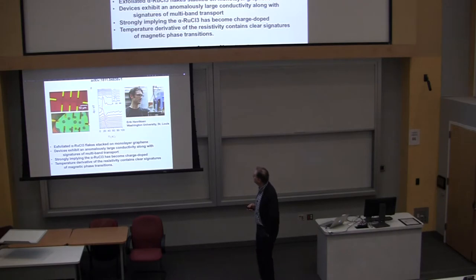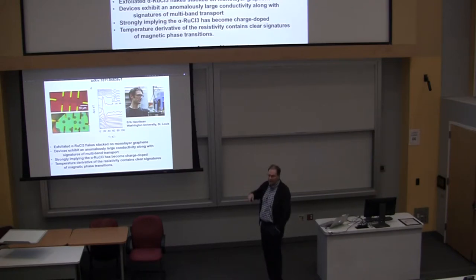The first thing he did was realize that ruthenium trichloride is actually fairly stable in air in one and two layers. And then very recently, he put exfoliated ruthenium chloride flakes and stacked them on top of monolayer graphene. And basically what he observed was charge transfer from the graphene to the ruthenium trichloride. This is actually a very important discovery, because it's usually really hard to metallize some of these systems. And so he metallized the ruthenium chloride by placing it in proximity to the graphene.